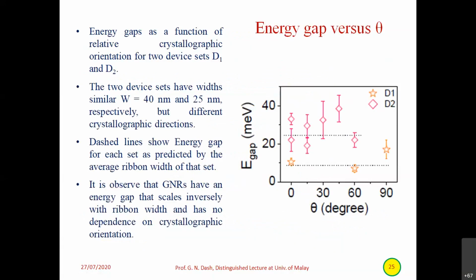Now, energy gap versus crystallographic direction. Energy gaps as a function of relative crystallographic orientation of two device sets called D1 and D2 are shown. These two device sets have similar widths, 40 nanometer and 25 nanometer, but different crystallographic directions, and the dashed lines show the energy gap for each set as predicted by the average ribbon width of that set. You can see that the thing is the average. So you observe that the energy gap scales inversely with ribbon width and has no dependence on crystallographic direction.